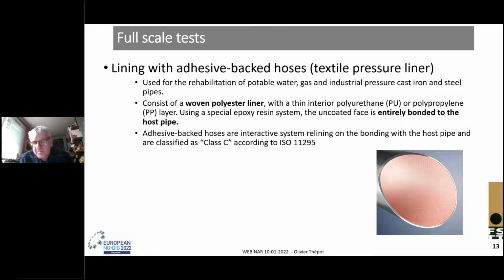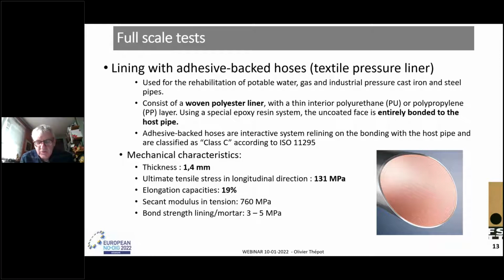relining on the bonding with the host pipe, and are classified class C according to ISO 11295. Regarding the mechanical characteristics, it can be noted that the thickness of the liner is low, only 1.4 millimeters, and that its tensile strength is very high, as is its maximum elongation, which reaches 20%. On the other hand, the secant modulus in tension is low. We will see that these characteristics are in fact very well suited to gap opening load.